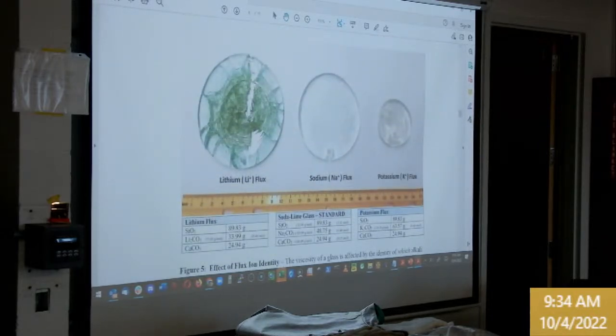Another reason we don't pour these anymore is lithium is such a potent flux that it actually is very damaging to the inside of the furnace. That's part of my problem here. So I've fluxed with lithium. If you look here at the top element of the furnace, you can see that it's cracked and caving in. Well, the ceramic in a furnace is also ceramics. It's silicates and alumina and zirconia. It's also susceptible to fluxes. So if you have fluxes that are able to vaporize, they actually embed in the brick, and because that one is bearing its own weight, it's not like it's load bearing for the furnace, but it's bearing its own weight, it actually droops and sags. And so lithium, you've got to be careful. It's a fairly potent flux that can soften the brick in your furnace.